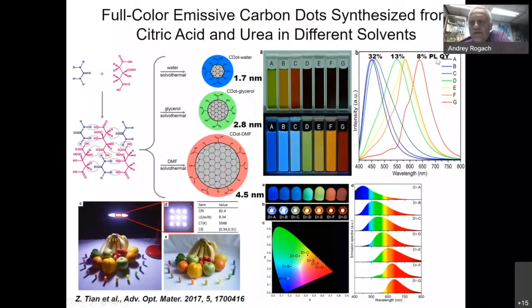So when we look at photoluminescence quantum yields here, blue emitting particles have highest numbers here, red emitting particles have lower ones. 8% is kind of okay, right? I claimed before that we can make 80% for blue emission, and this is indeed possible. 30+% is still a good number. So here, when we move to longer wavelengths, photoluminescence quantum yield drops, but this still allows us to make strongly emitting composites out of these materials when we put them into polymer matrix.